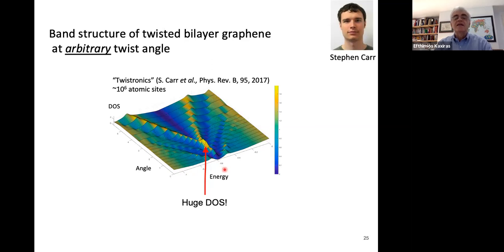And notice that this now is at the Fermi level. So you don't need a lot of doping to access this very high density of states created by the small twist angle of roughly 1 degree in the twisted bilayer graphene system. So this was very exciting when we saw this. So we coined the term twistronics to describe this.